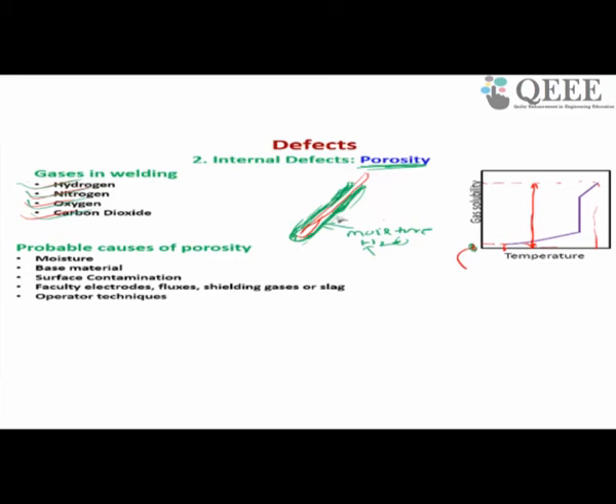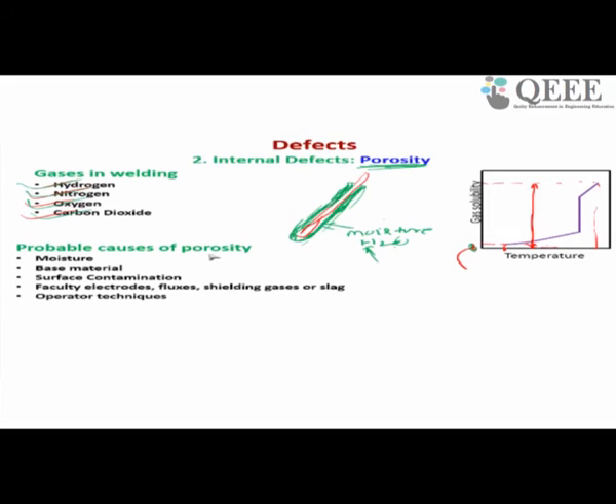So when you do welding with this kind of filler material, even in the presence of an inert gas like helium or argon, still because of the moisture present in the electrode, hydrogen will dissociate from the water molecule and be absorbed in the weld pool. As a result, it causes porosity. Similarly, other parameters in the flux, and operator technique, may also cause gas to be entrapped in the weld pool. Okay, this is about the generation of porosity.